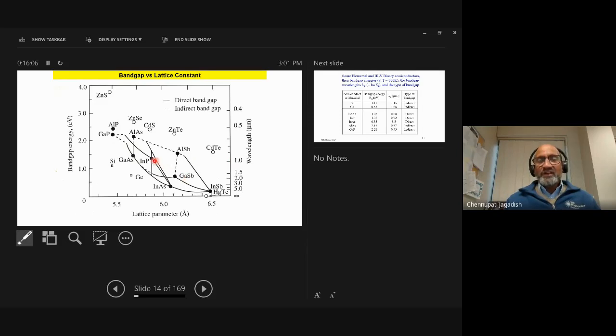Whereas in the case of indium phosphide, you can see that indium gallium arsenide with a particular composition, 53% indium, is lattice matched to indium phosphide. It becomes easier to make lattice matched structures. If you try to deposit a material on another with a different lattice constant, you essentially create a lot of strain. And beyond a particular thickness of that layer, you end up with dislocation formation and other things. So then it becomes useless as far as optoelectronic devices are concerned.